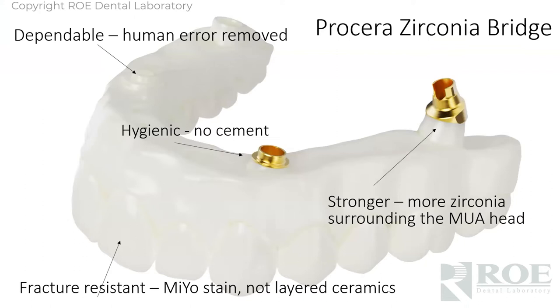The zirconia around the prosthetic adapter — most of the cases we work on are at MUA level. If you don't have a coping inside, you have more material. Everybody wants a Procera bridge to be narrower buccal-lingual, but you can't sacrifice it because of strength. Well, if you don't have a coping inside, then you add another millimeter at least with cement and material space, so it's much stronger.